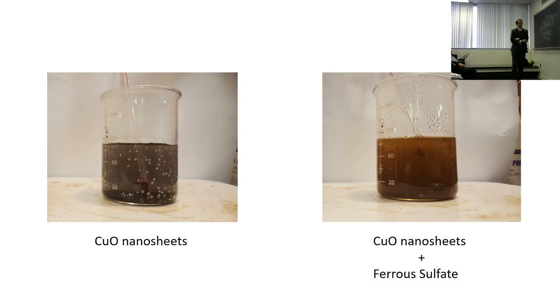But I would mix it with other things, and one thing I mixed copper oxide with was ferrous sulfate, Fe2+. And if you mix it with ferrous sulfate and you heat it up, your solution turns orange. And chemists and chemical engineers get excited about color changes because it means something happens and you can see it. It's kind of cool. And when you mix copper oxide nanosheets with other sorts of salty solutions, you don't get this. It just, nothing happens. It's kind of boring. So I was excited about the ferrous sulfate.